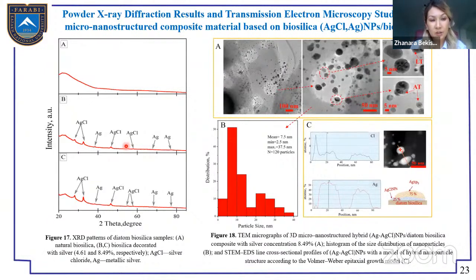And for the formation of silver chloride and silver nanoparticles, the mineral composition was presented in the figure, and the broad peak of the opal A, this amorphous silica from 20 to 35, and the formation of silver chloride and metallic silver nanoparticles on the surface of diatomaceous biosilica presented in the figure.